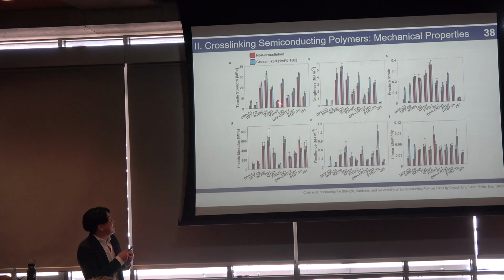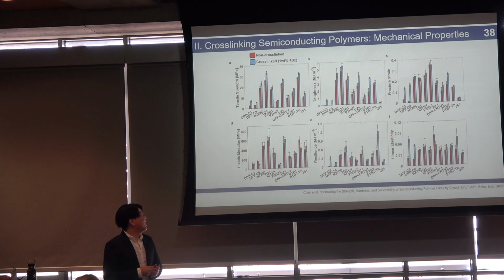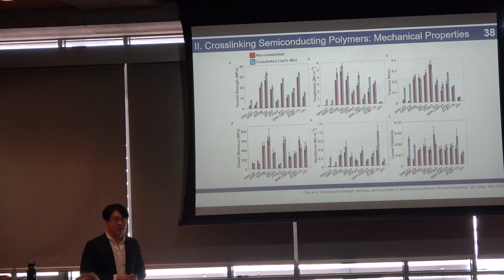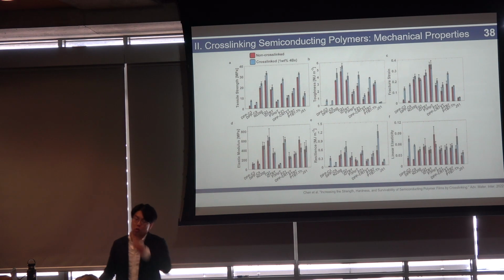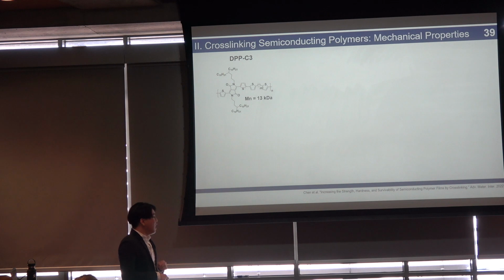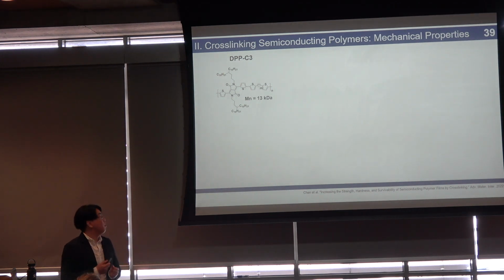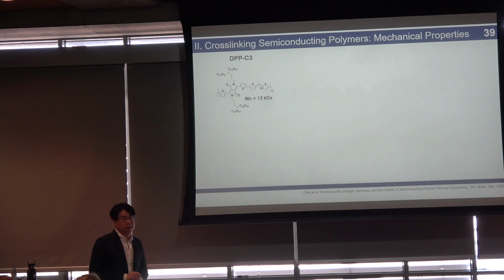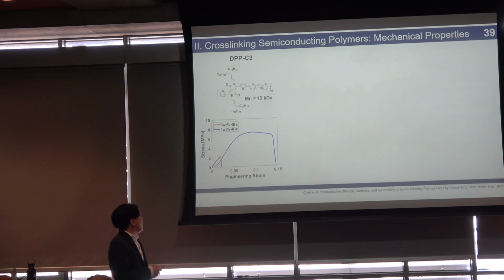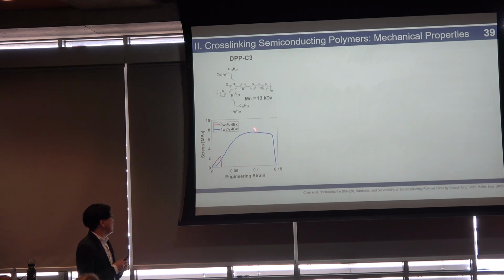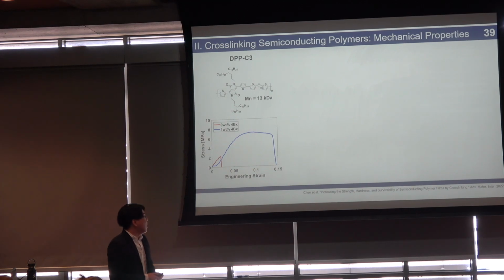What matters most is these blue bars, which are cross-linked films, are taller than the red bars. And what that means is, in general, over all these extracted mechanical properties, your cross-linked films are more mechanically robust than your non-cross-linked films. In particular, we saw a big improvement for polymers that had a very low molecular weight. So this is DPP-C3, and it has a molecular weight of 12 kilodaltons. And we saw that when you cross-link your film, you get a huge increase in your mechanical robustness, in your stretchability, in your strength, in your toughness, which is the energy that can be dissipated.